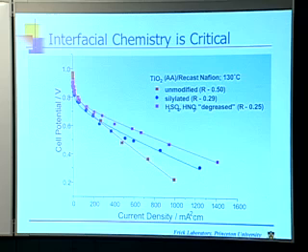Then we took the good material, and we hit it with trimethylchlorosilane to put an organic layer on the surface. There are surface TiOH groups on the titania, and so we're reacting those with the chlorosilane bond and putting trimethylsilyl groups all over the place. And when you do that, you see a degradation from the nice magenta curve to the blue curve. It's starting to move down.